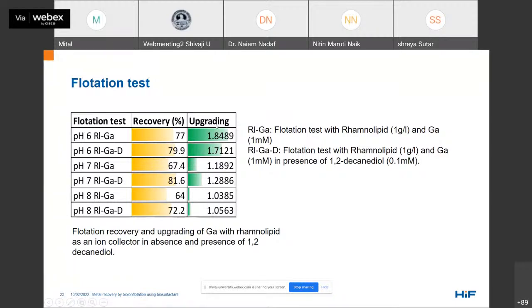This upgrading factor is an important parameter when considering flotation recovery in the presence of other metals, like when we are talking about industrial wastewaters or model solutions with different metals. So for a flotation process with a metal mixture, the higher the upgrading value for the target metal as compared to other metals, the higher the selectivity and process efficiency. So we would go for optimizing parameters where the upgrading value is higher as compared to recovery, because if the upgrading is higher, you will selectively recover your target metal in higher amount.